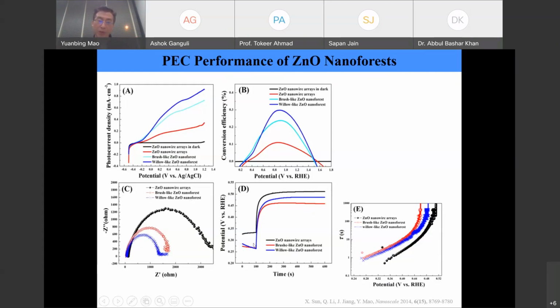And then we also look at the conversion decay time as well. There are a couple of things we look into if we look at D and E together. We can see that the zinc oxide nanowire arrays have a higher potential, but the decay time is the longest, right? So that gives more time for the charge carriers to recombine, right? While for the two nanoforest samples, the decay time is actually shorter.